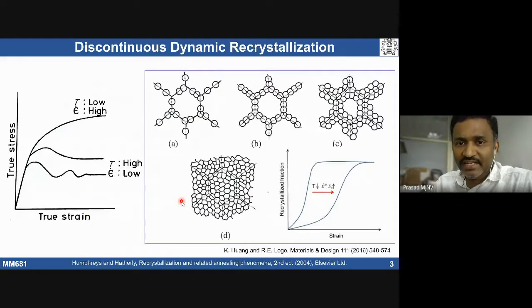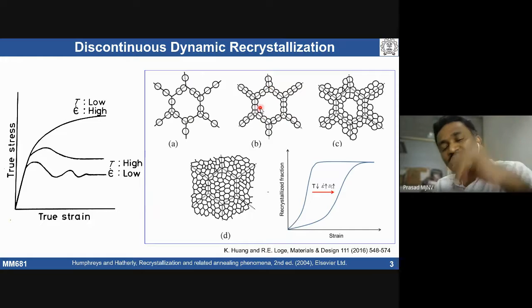So in case of DDRX, one characteristic feature you see is how the stress-strain curves look like this, and microstructurally, this necklace kind of structure is going to form. Strain-free grains form along the boundaries of the deformed grains. Whenever the onset of recrystallization takes place, there is some onset strain. At that strain we see recrystallization happening. If you stop and look at the microstructure, we see formation of this necklace kind of structure, strain-free grains along the boundaries of a deformed grain structure.